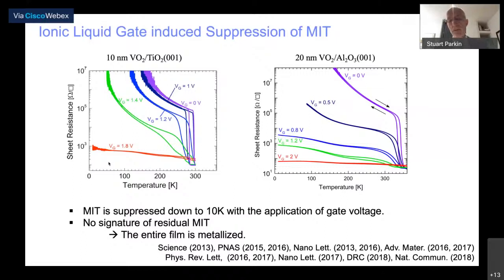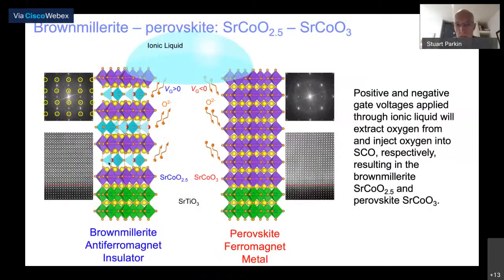to low temperatures. And we showed in a paper we published in Science in 2013 and in all these subsequent papers, this is due to the removal of oxygen from the vanadium dioxide film. And that removal happens over up to 1 micron from that surface interface with the ionic liquid. Let me just hurry on.